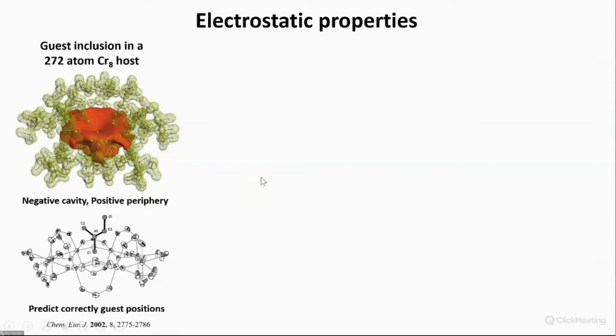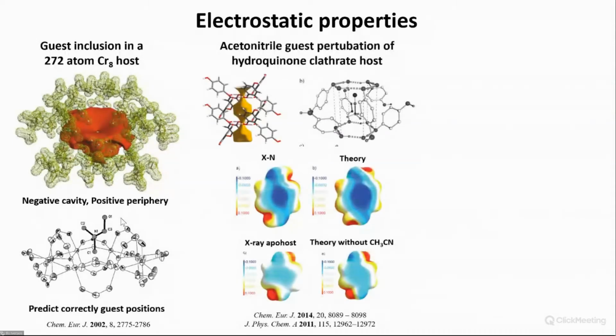And we then synthesized 5 different compounds to see how the guest inclusion would be in such a host structure. And the guest atoms, for instance, here put the negative oxygen away from the negative center of the host molecule. And in all those 5 cases, we from the electrostatic potential could at least give a first prediction of guest positions. If we look again on electrostatics, here's another example, 2 papers on the hydroquinone.